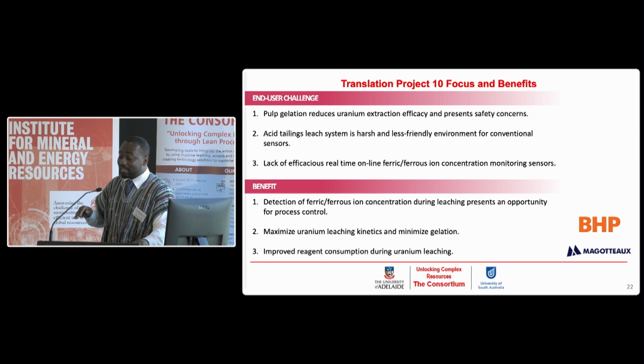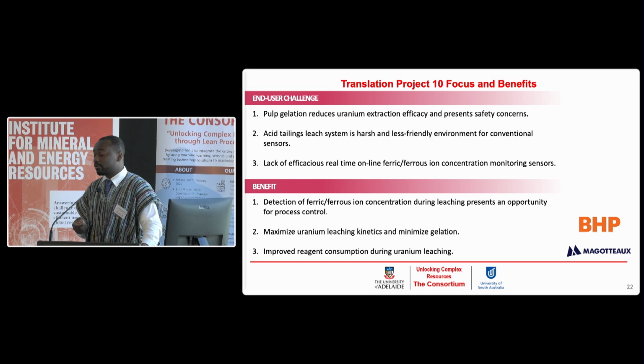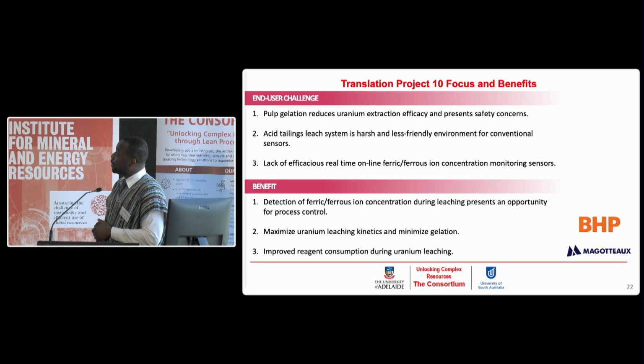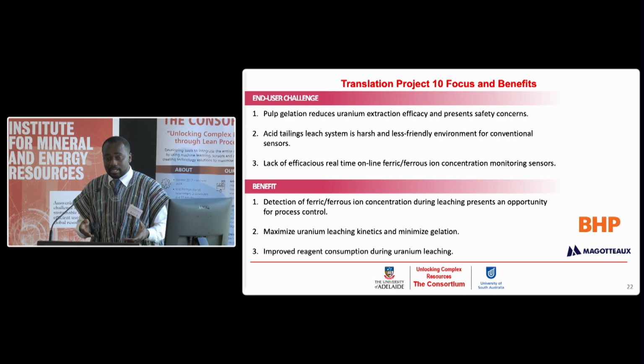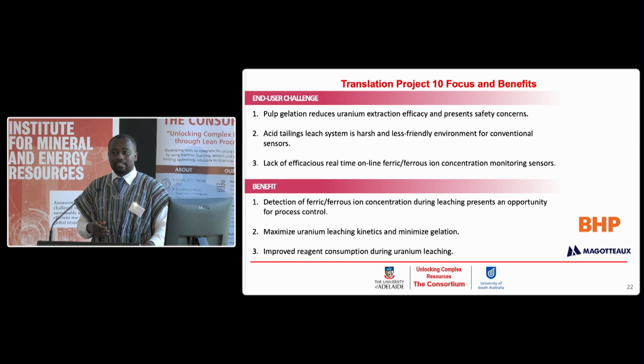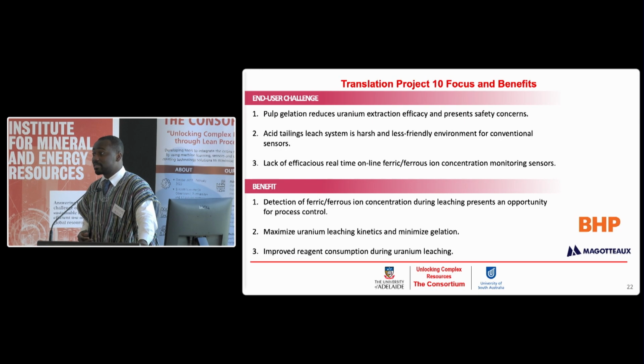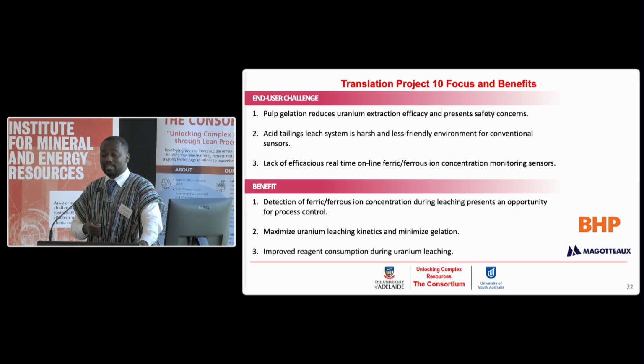But what happens then is that you are now leaching at very aggressive conditions, and that can cause other species to also dissolve in the solution and enhance pulp gelation. That's a major issue which we are trying to properly monitor with a sensor of this sort. Currently, because the leaching environment used for uranium is highly acidic, pH 1, and at high temperatures, you don't have a suitable sensor that can be installed to monitor this continuously. It will just break down. So having a MOF sensor, which is very effective in that system, will be very useful and can help in controlling the process.